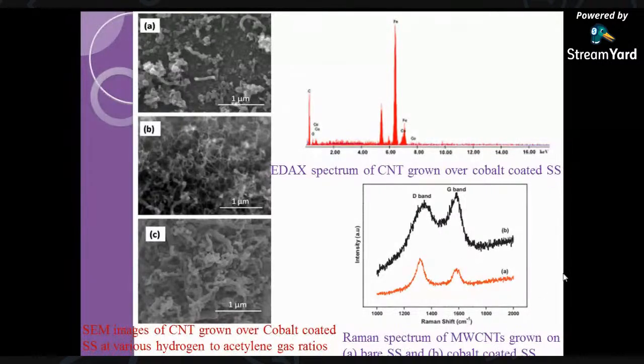So if you look into this Raman spectroscopy, you can see two bands coming out of this. One is a D band and a G band. And this G band indicates the graphitic structure, graphitic carbon, around 1,500 to 1,600. And you have a D band, which means you have some defects in your carbon, coming between 1,200 and 1,400. So this peak indicates the presence of both graphite, we have a dominating graphitic structure, and we have a few amorphous carbon in our product.